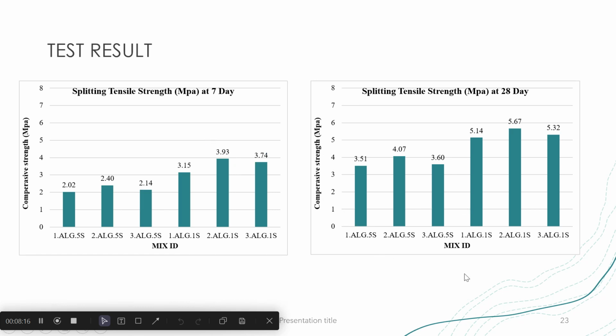And for the other test, splitting tensile strength, after the 7th day we have 2.02 for the first mix, and for the 5th mix we have 3.93 megapascal. And after 28 days, the high value for splitting tensile strength is 5.67 megapascal.